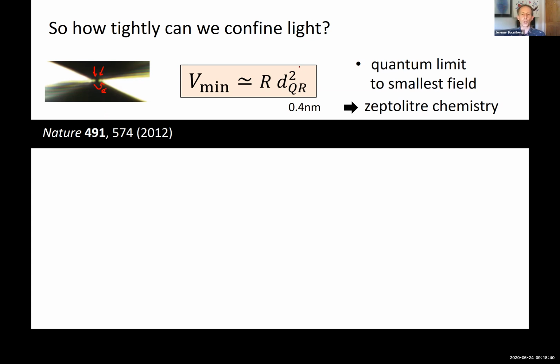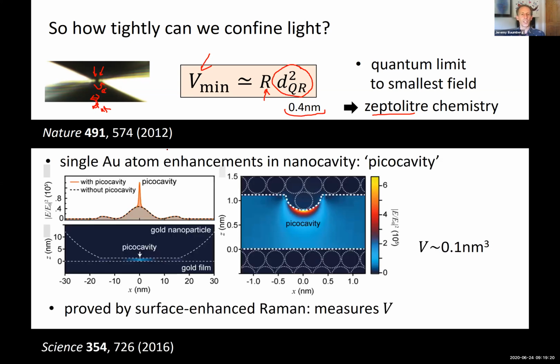So what that means is there's a quantum mechanical aspect to how tightly you confine light, which is given by when this quantum mechanical tunneling starts. So this d_QR, this quantum mechanical tunneling. So d_QR is on this order of about 0.4 nanometers. It's not very easy to change. And you also have the diameter or the radius of the nanostructures that you're looking at there. So that's what we thought was the very smallest size that we could ever confine light, on the order of tens of nanometers cubed. And so that still allows you to do something like zeptoliter chemistry. So it's not big.